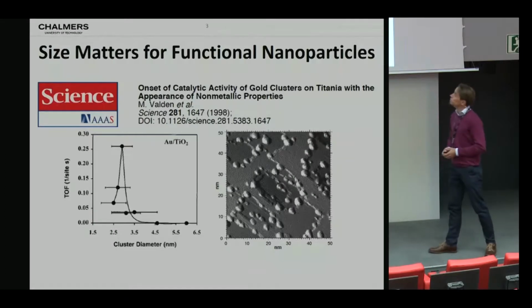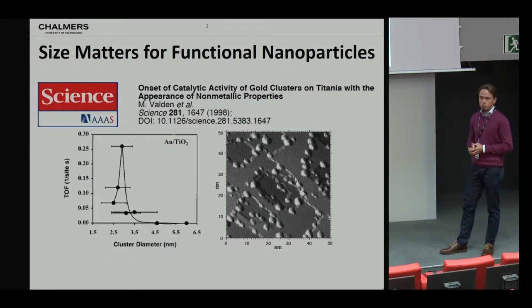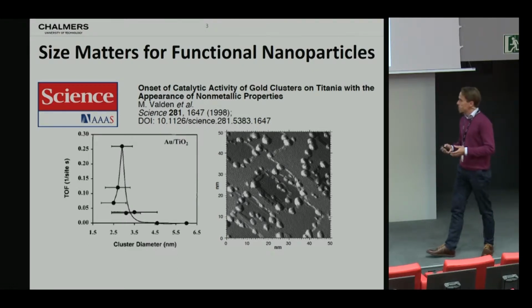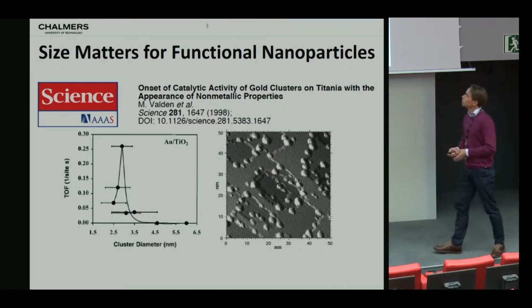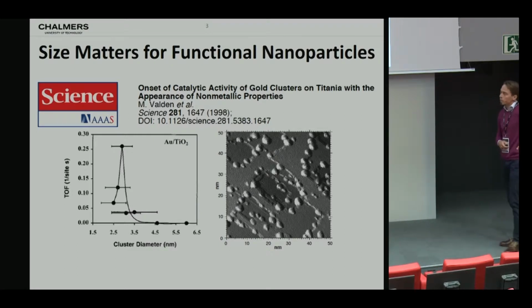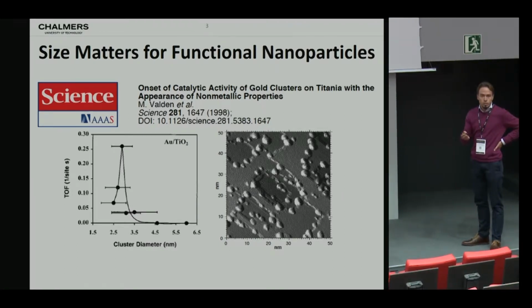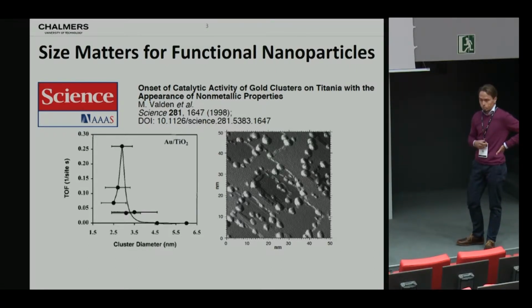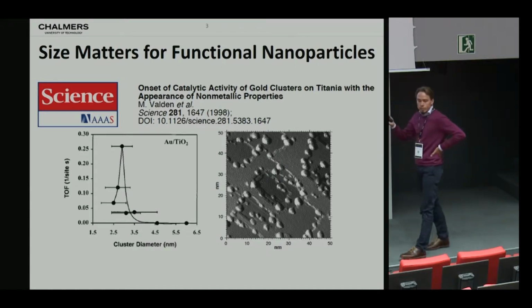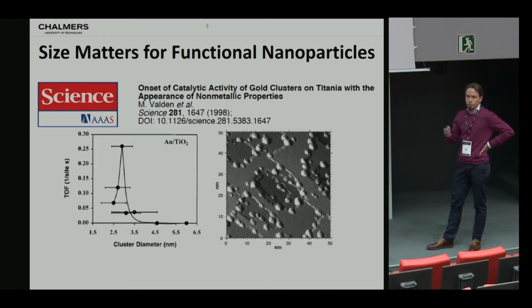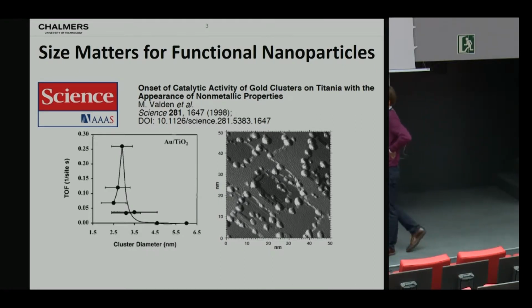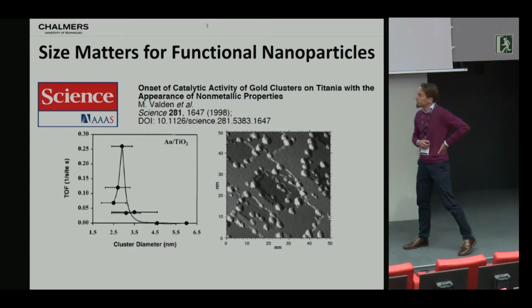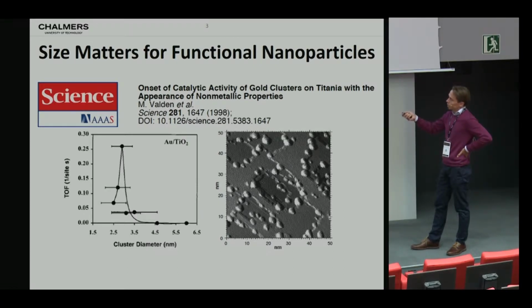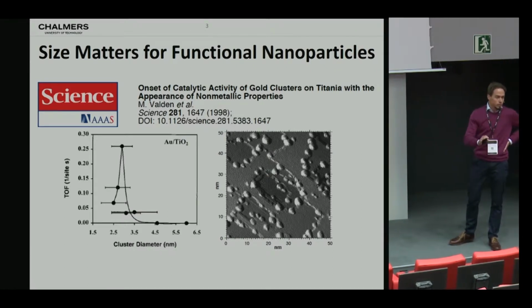Well, for example, for many functional nanoparticles, size or shape matters. And one of the most beautiful examples, for me, to illustrate this is this work from Wayne Goodman's group from '98, where they take gold nanoparticles, and you all know that gold is chemically quite inert, which is the reason why we use it so much in plasmonics. But if you make gold nanoparticles and you put them on a titanium dioxide surface, and you investigate whether or not they catalyze the oxidation of carbon monoxide to CO2, which is one of the most important catalytic reactions taking place in the three-way catalytic converter of any car, then you will find the following. As you would expect for gold being chemically inert, down to a particle size on the order of about 4 nanometers, this material is catalytically dead. It does not catalyze the reaction.